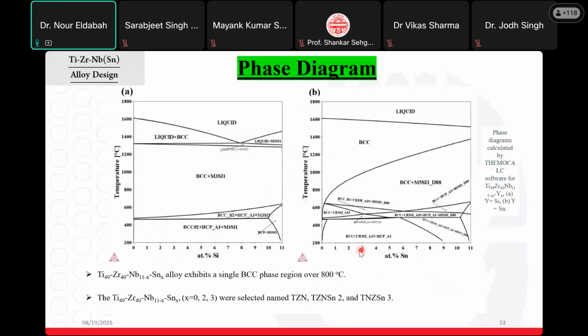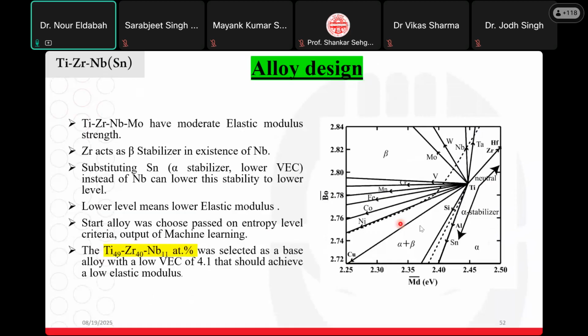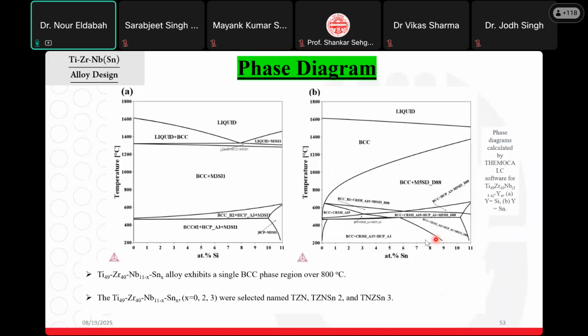We consulted the phase diagram, and we plotted after we chose silicon. We excluded aluminum because of its negative effect. We made a calculation for silicon and tin, and we have two phase diagrams here, one for the silicon and the other one for the tin containing alloy, titanium, zirconium, niobium base.